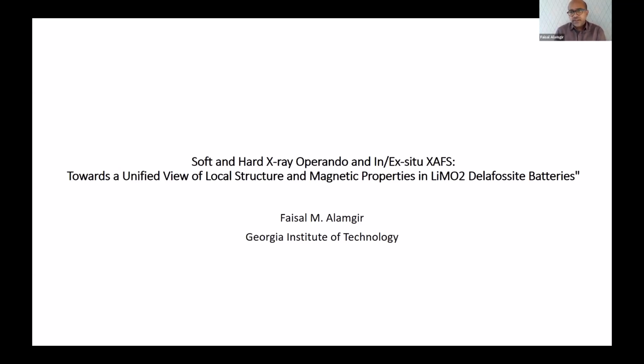And of course, there are other interests in these types of compounds as well, because the alkali ions can essentially be titrated in and out of compounds, either chemically or, as we later found in the battery cases, we can use the working of the battery to control the stoichiometry of lithium in these compounds fairly accurately. In doing so, we can change the intrinsic properties of the compounds themselves. So there's a lot of fundamental physics and chemistry that can be triggered by the amount of alkali ions present. And so as a playground for studying materials properties changes or structure property relationships, these cathode materials are very interesting.